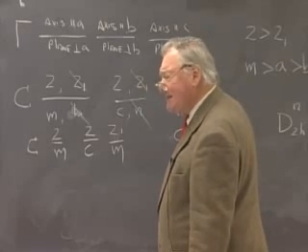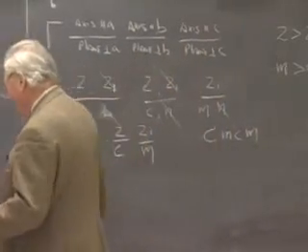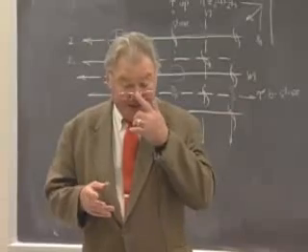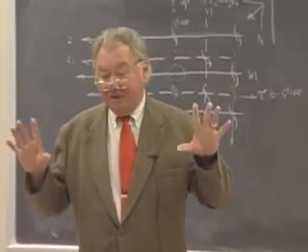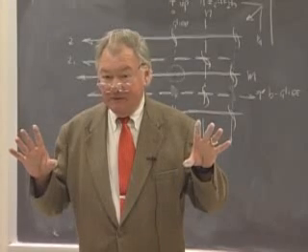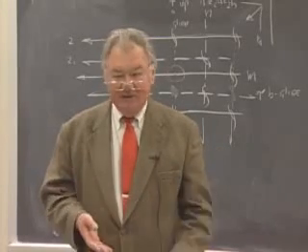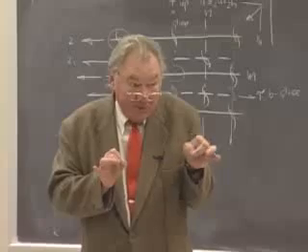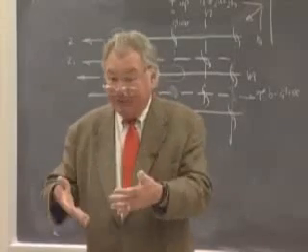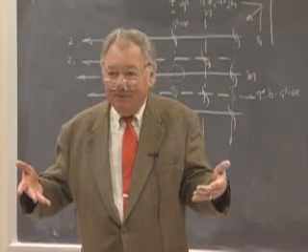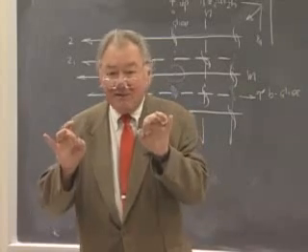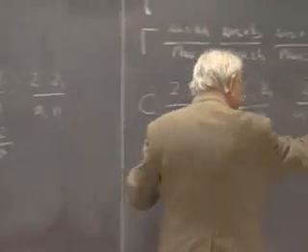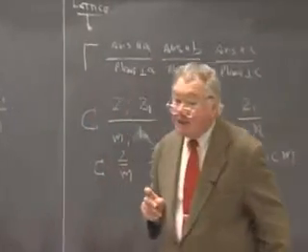And when you start out in diffraction, many people have a first disconcerting experience. You spend probably the better part of a month taking single crystal diffraction patterns. You come up with a trial space group for your particular material, and then you go to the International Tables and you say, it's not in there. What did I do wrong? And you go back and you check all your calculations. You look once more at all of the systematic absences of reflections. See, I have it right. Why is it not in there? Well, the answer is more than likely that you have a different setting for the labels that you apply to the axes, and you have therefore metamorphosed the symbol for the space group from one form to a symbol that is very, very different.